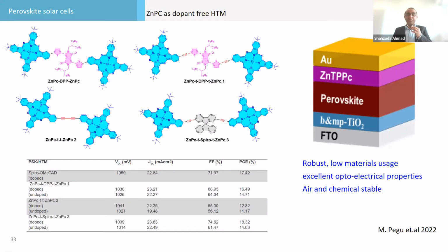Similarly, I think Meenakshi has been working on phthalocyanine, because we know phthalocyanines are not very conducting, but they are very stable, and they also have very good, very sharp color. So with the dimer of phthalocyanine, we have been optimizing at doped and undoped stage, and 18.32 we have reached. Undoped is 14.03. The ideal will be the undoped stage, so the device performance can remain stable, but sometimes it's not the case for making high performance.